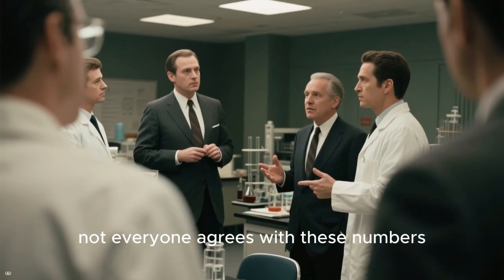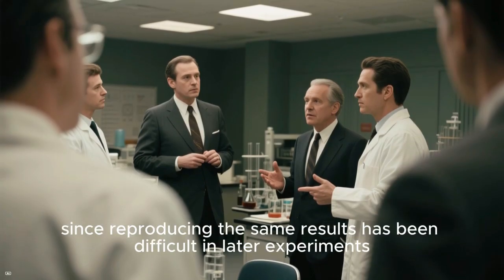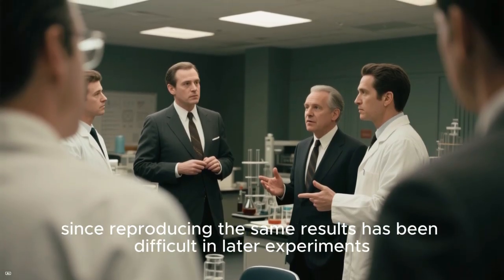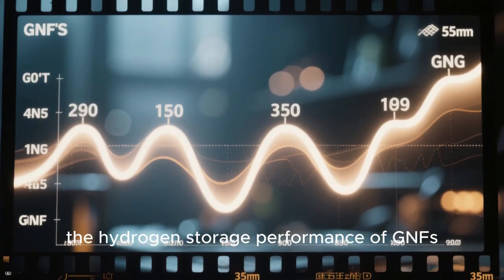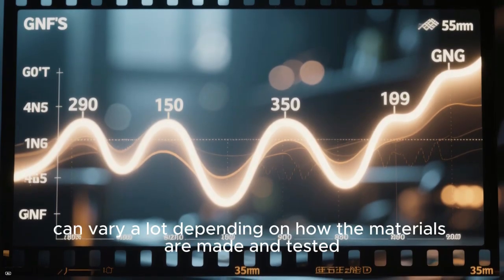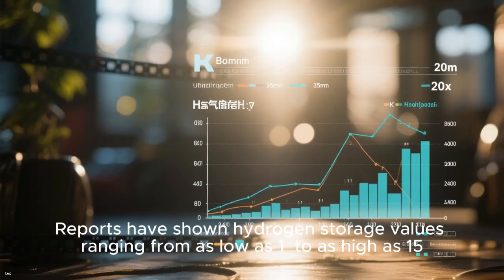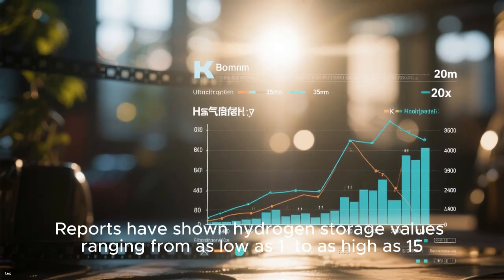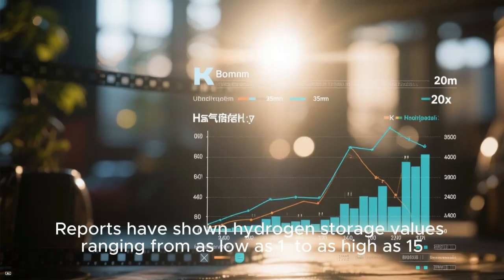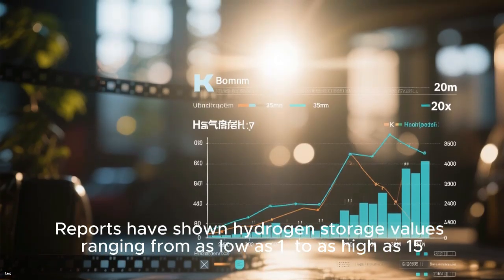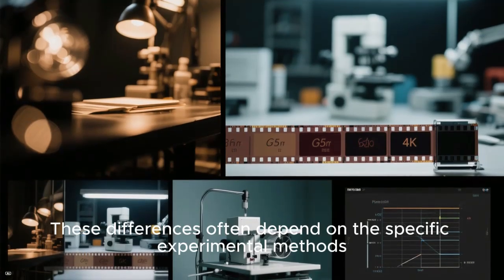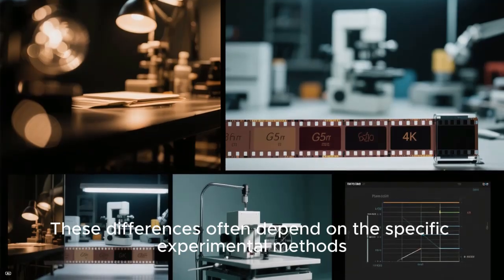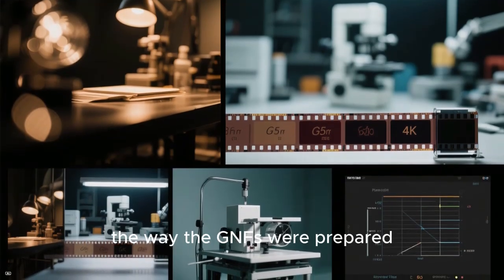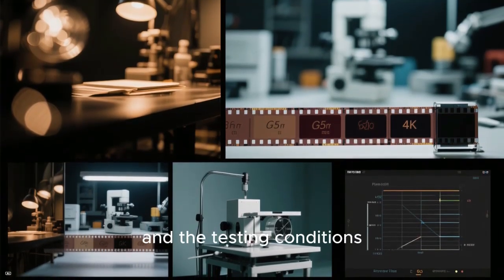However, not everyone agrees with these numbers, since reproducing the same results has been difficult in later experiments. In general, the hydrogen storage performance of GNFs can vary a lot depending on how the materials are made and tested. Reports have shown hydrogen storage values ranging from as low as 1% to as high as 15%. These differences often depend on the specific experimental methods, the way the GNFs were prepared, and the testing conditions.